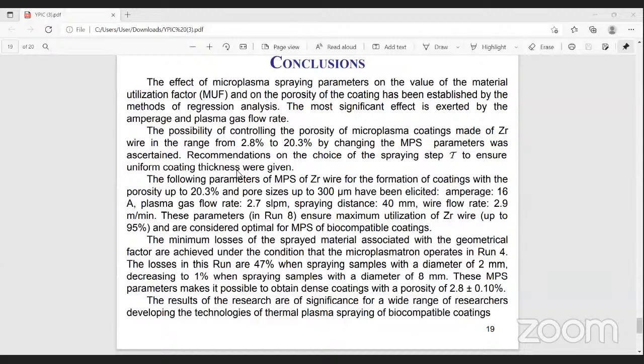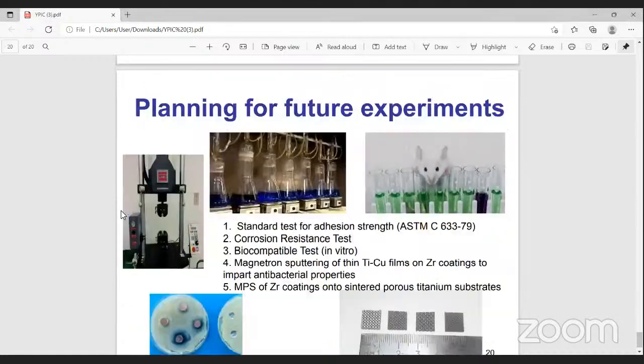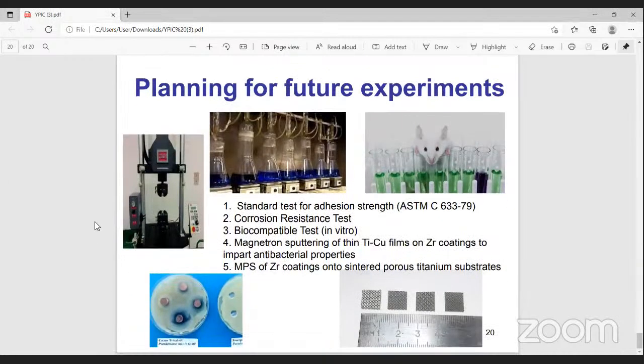The possibility of controlling the porosity of microplasma coating made of zirconium wire in the range from 2.8% to 20.3% by changing the microplasma spraying parameters was ascertained. And here are plans for the future experiments. Thanks for your attention.